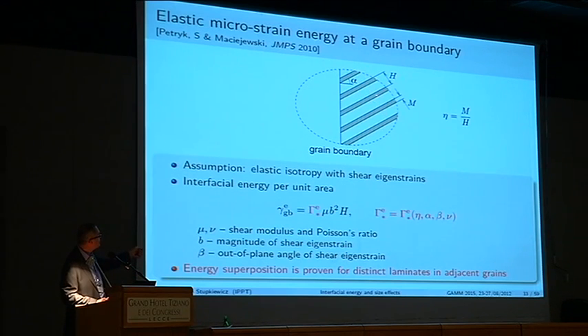the volume fraction of the plates, of the martensitic plates, is also changing during the transformation. So there are a lot of unknowns, therefore we simplify the problem here, and we adopt the assumption that we have elastic isotropy, which helps reduce the complexity significantly for us. So at the end, we can compute the grain boundary energy using this kind of dimensionless energy factor gamma star, which now depends only on four parameters. It's still a lot, but it's less than it would be without this simplifying assumption. So eta would be the volume fraction. Of course, it must depend on the volume fraction. Alpha is the inclination angle, a geometrical parameter. Beta determines the orientation of the shear strain with respect to the plane of the analysis. So again, we consider a fully 3D situation, just in a 2D problem, but with all 3D stress and strain fields. And nu is the Poisson's ratio.